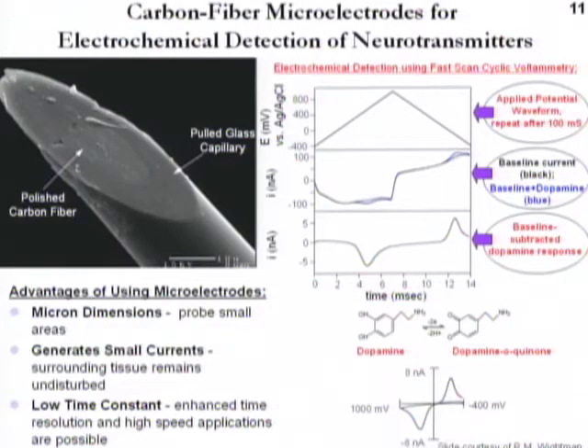So that was a general idea of voltammetry. For neurochemical sensing, you have to speed up the scan rate to be on the order of hundreds of volts a second. This particular piece of data was taken at 300 volts a second. That means that entire scan only takes about 10 milliseconds, and thus we can actually do voltammetry during a single neuronal event.